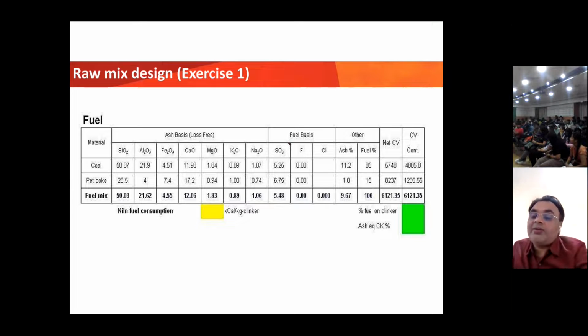You have to see which raw materials have less burnability, right? Which is easy burn, and which is very hard burn, because high fuel will be consumed in that case. So finally, coal is being used. Coal is used at almost 11 to 12% of whatever clinker is produced. That 11 to 12% of fuel is consumed to burn the raw materials, right?